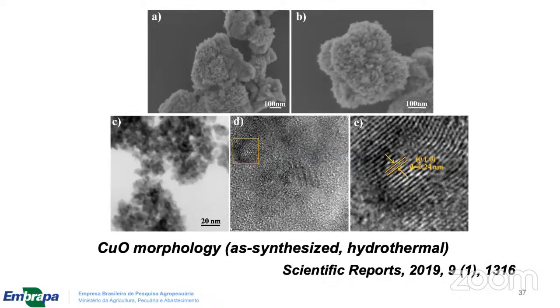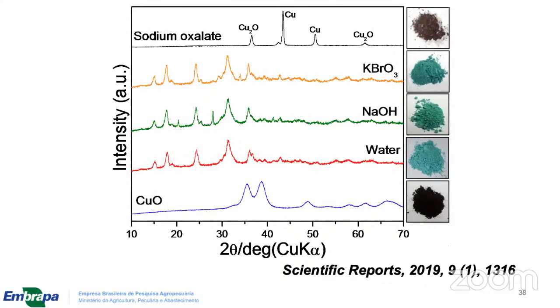So, to confirm this hypothesis, we have produced different copper oxide morphologies with very high surface area. All of them are copper oxides, and we have submitted these materials to different conditions of reduction. For instance, this is the starting material, just copper oxide. We have done the CO2 reduction reaction using water. We have observed after the reaction a transformation of this material to another phase. We have tried this in an alkaline environment using sodium hydroxide and CO2 again. We have tried to use an electron suppressor, potassium bromate, to understand what we would produce in the system, and a hole suppressor with sodium oxalate.